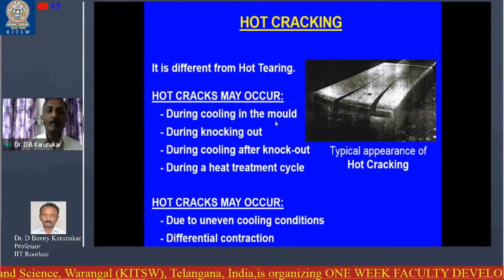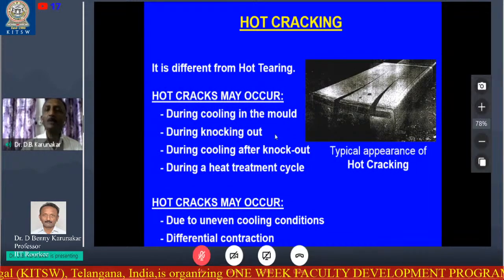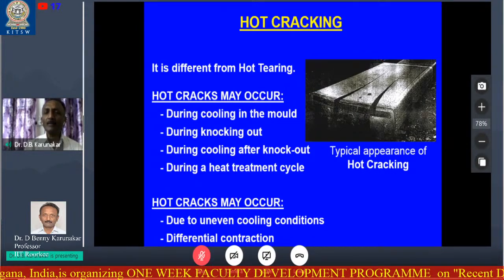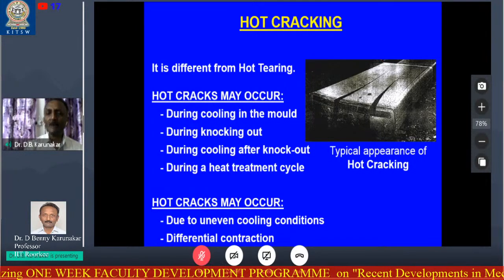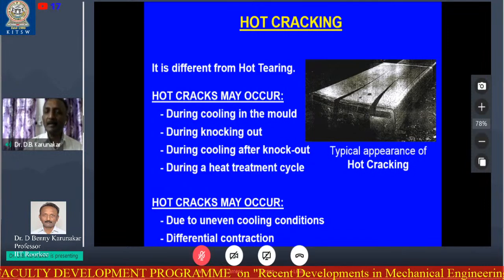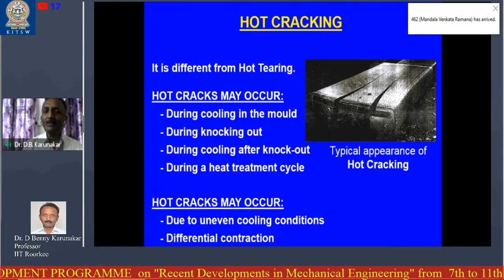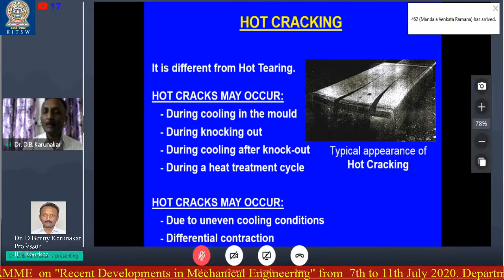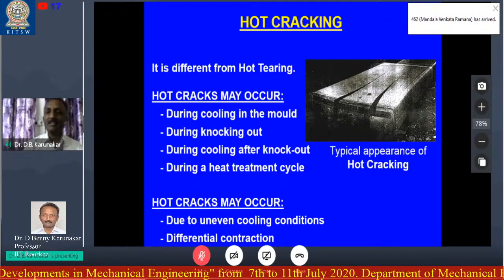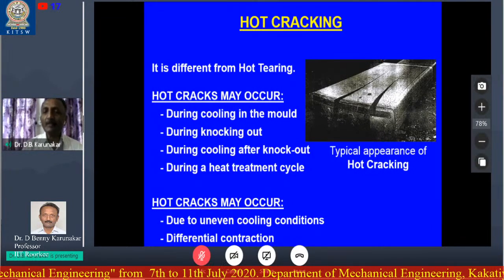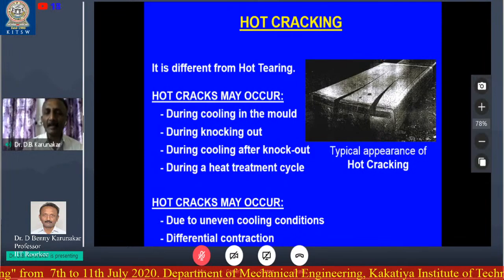During cooling in the mold, during knockout. During knockout, after solidification is over, we break the sand. During the breaking, if it is too rough, someone can hit the solidified casting, and it can undergo cracking.